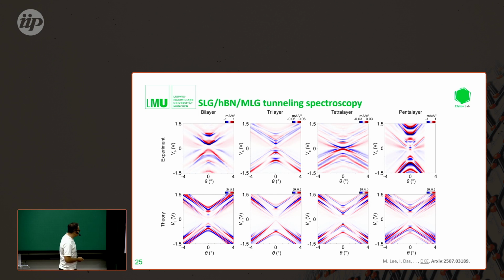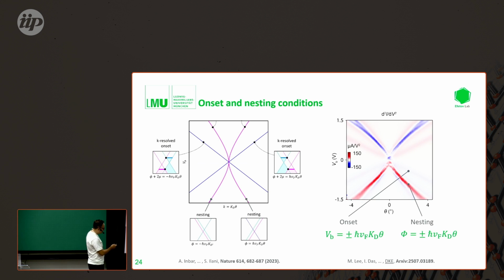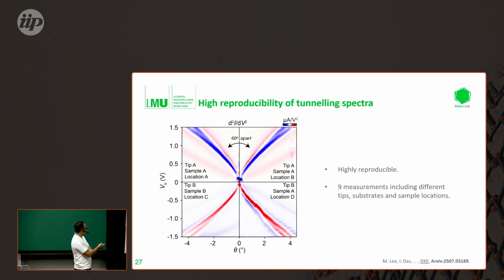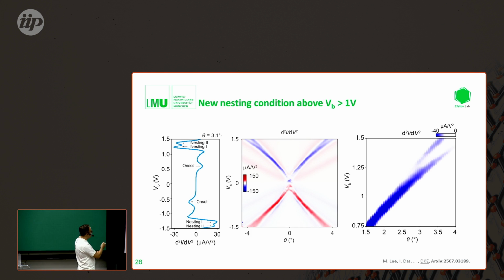And as I maybe explained on this slide, in principle, the nesting condition lives on the fact that the band structure of single-layer graphene is linear, and that the linearity persists quite far into K-space. So in a scenario like this, for a perfect Dirac cone, we should not see any second nesting condition, because the bands always have to run in parallel to one another. So first we scratched our head: what is this feature here that produces this nesting? But it was clear that this nesting is produced by some small nonlinearity.